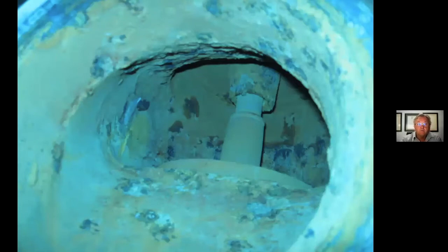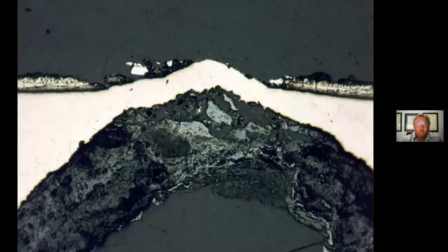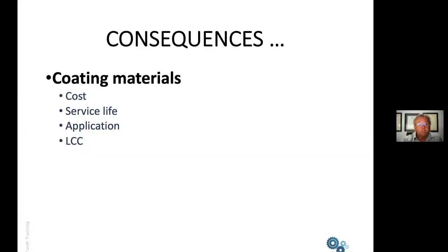This valve was made out of cast iron and had been put inside a cooling system that was made out of copper nickel. And the copper nickel that plated out on the inside of that valve set up a bimetallic corrosion reaction, and the net result was a failed valve. Here's an example of internal corrosion where the wall thickness only just held. You can see the effect of the internal pressure where this particular pipe was on the point of rupture.